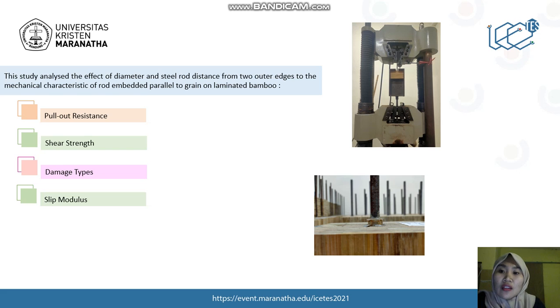This study analyzed the effect of diameter and steel rod distance from two outer edges on the mechanical characteristics of rod embedded parallel to grain on laminated bamboo. The mechanical characteristics include pull-out resistance, the shear strength, the damage types or damage pattern, and the slip modulus.